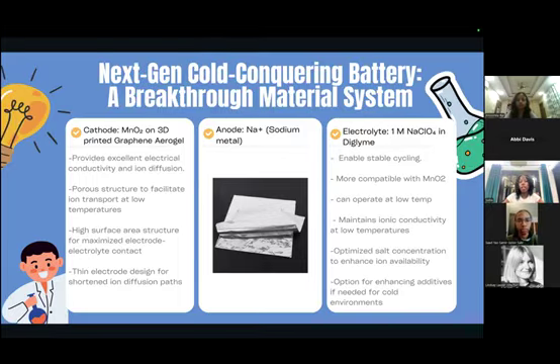Thirdly, for the electrolytes, we have sodium perchlorate in Diglyme, and this enables stable cycling, and also it is compatible with manganese dioxide, which is our cathode. And the fact that it is 1 molar in concentration improves the ion availability, and we can include additives if needed for a very cold environment.